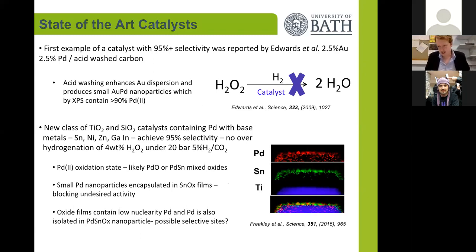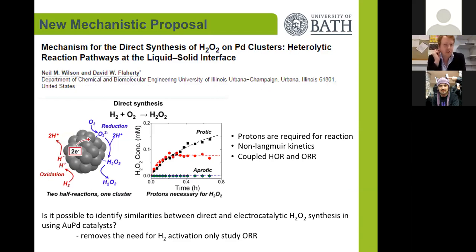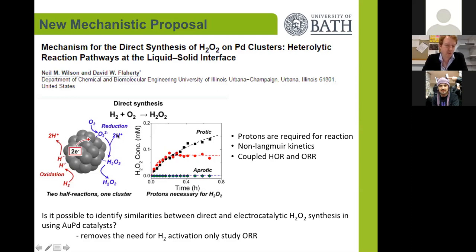At this point in our studies of hydrogen peroxide, we took a slight sideways step, motivated by a proposal by Flaherty published in JACS two or three years ago. In a very detailed kinetic study, it was proposed that the synthesis of hydrogen peroxide does not follow a Langmuirian type mechanism of purely surface reactions, but could actually be coupled electrochemical reactions. On the same palladium particle, you could be facilitating hydrogen oxidation to protons and oxygen reduction using protons from the solution and electrons generated from this hydrogen oxidation.